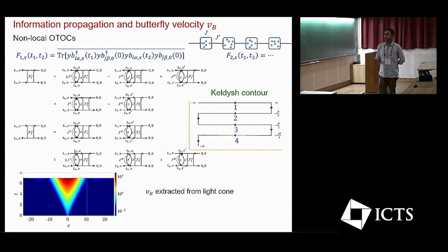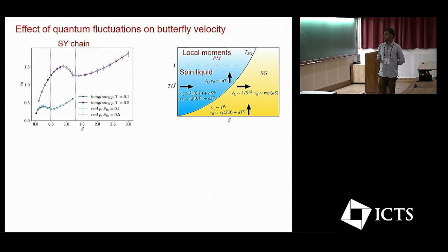At the end of the day you can extract this butterfly light cone that I showed earlier, and from that you can extract a butterfly velocity. So let me just discuss this result and I'll end. Basically, if you fix a temperature and look at this butterfly velocity as a function of s, then at small s it is the paramagnetic state. Initially it increases and then it reaches a maxima, then it undergoes a minima exactly at the spin glass transition, and again in the spin glass phase it increases like that.